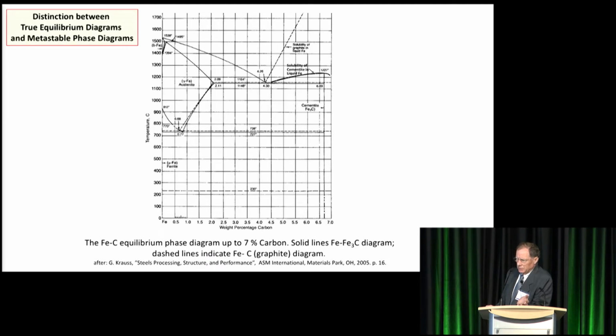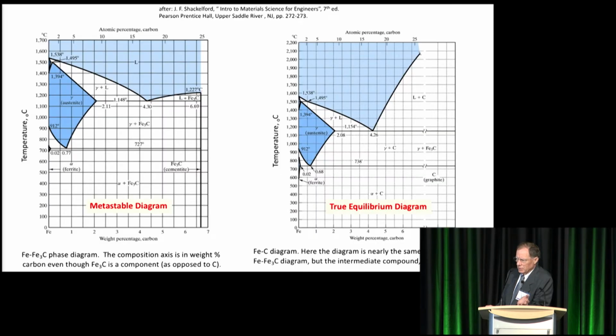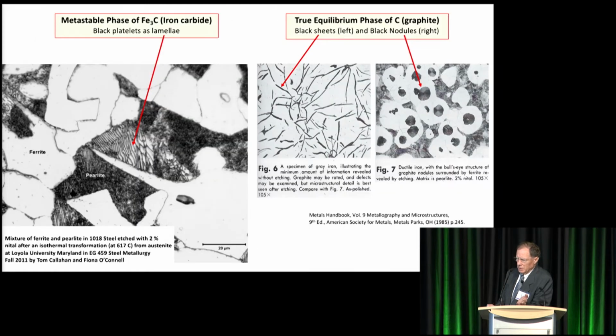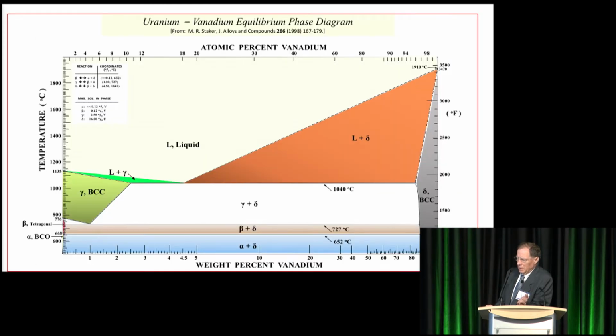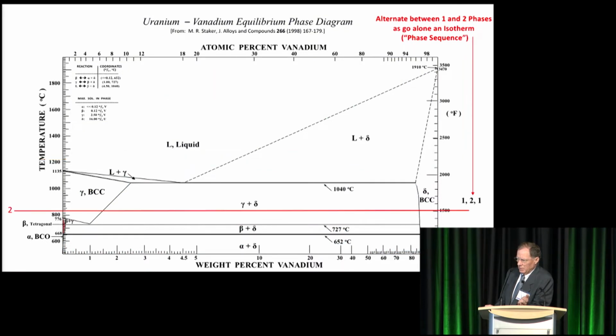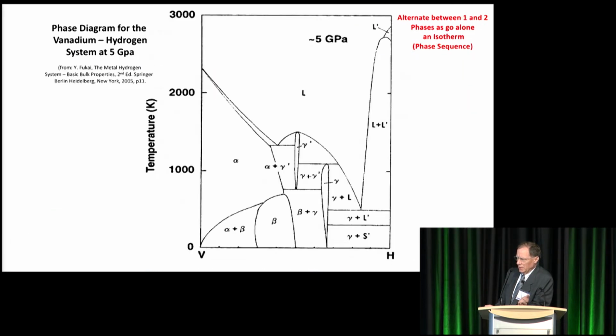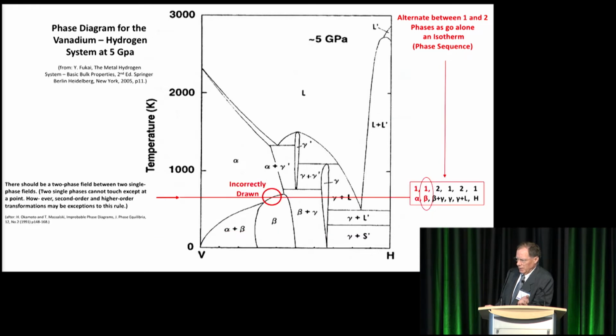This is 2 diagrams, one metastable, one the true equilibrium diagram for iron. This is the same thing shown in 2 separate diagrams, but there's a metastable diagram and equilibrium diagram. Both are useful. In fact, we use that to heat treat alloys, and I'm going to skip this example with uranium, but basically it's demonstrating the phase sequence, which is a necessary condition that you alternate between 1 and 2 phases as you go along an isotherm.